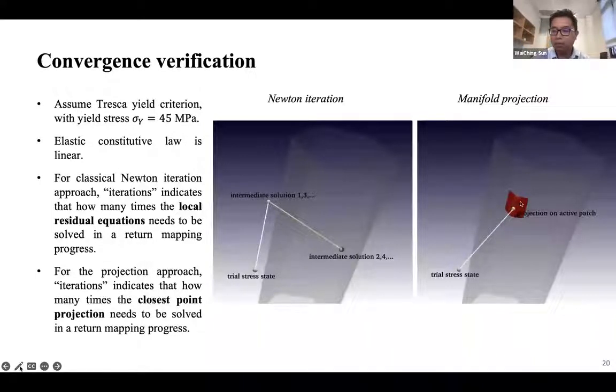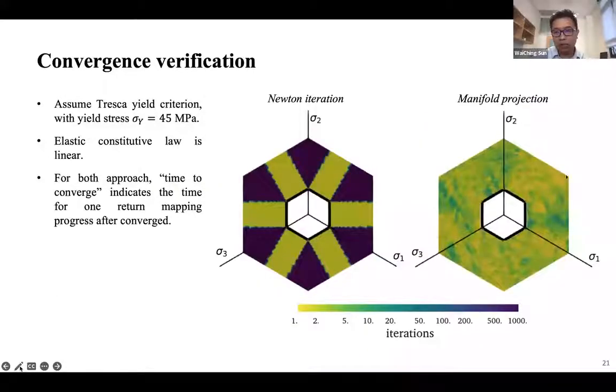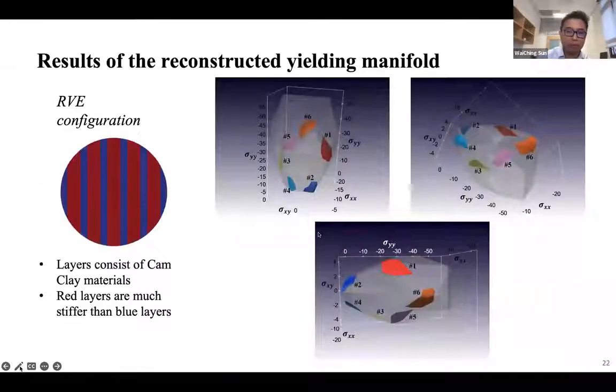But in the projection-on-the-patch problem, we can bypass this and locate the correct yield surface. You can see the iterations can be significantly reduced for the material that has linear elasticity or nonlinear. The key point is that this geometrical feature and the local definitions can help us bypass the iterations.